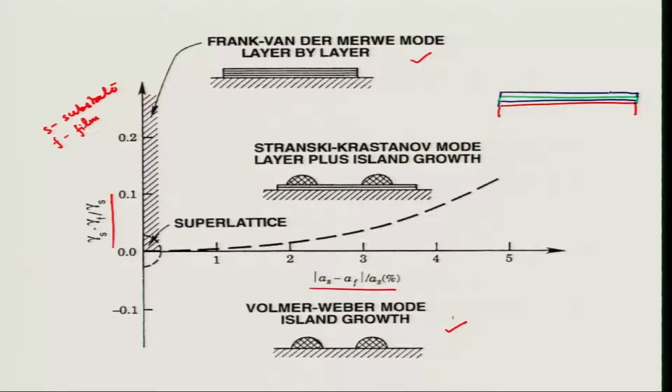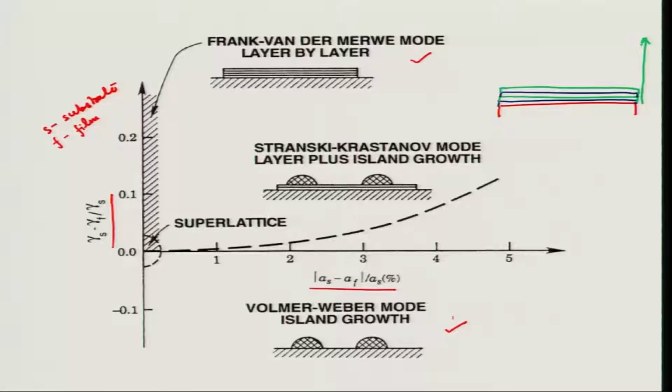Again, there will be some strain, but then you can switch back to another composition of a different material or different composition such that this strain is nullified. So, if one layer has compressive strain, the second layer has tensile strain. Overall in repetition you can keep building this up, with very thin layers, 1 to 10 nanometer thin, and you can build different layers, and this is what is called a super lattice. This also has various applications in solid state optics as well as electronic materials.